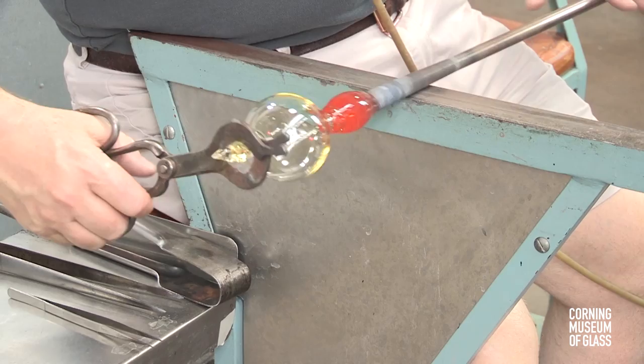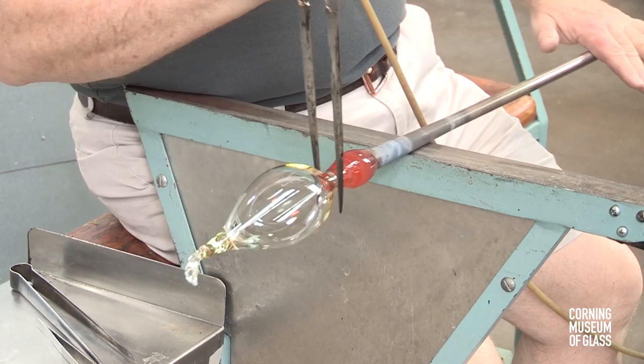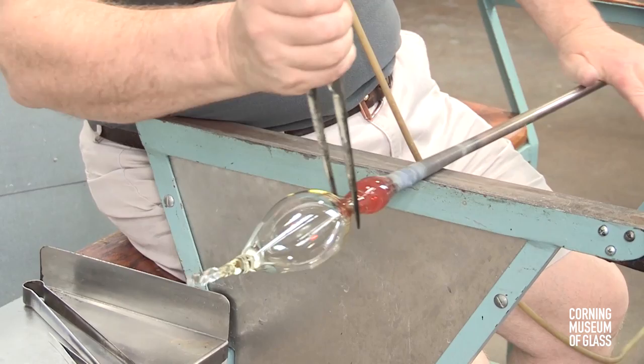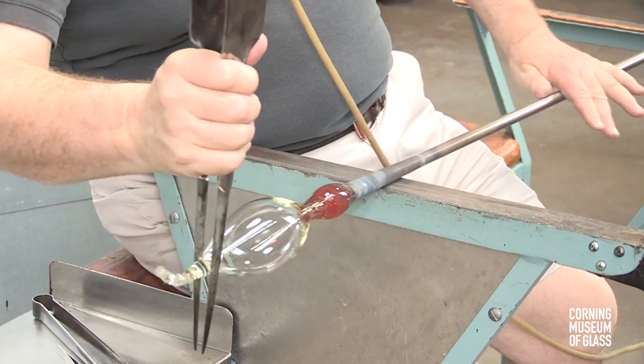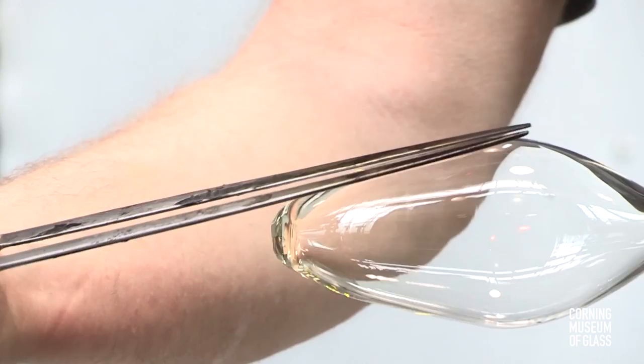The glass is inflated and then suddenly pulled outward. The constriction is refined in shape — it needs to be of narrow diameter, and the shoulder needs to be tapered. The tip is tooled, the excess glass broken off, the lower half reheated, and using the jacks as a sort of a mold, the glass is inflated and moves outward into the jacks.